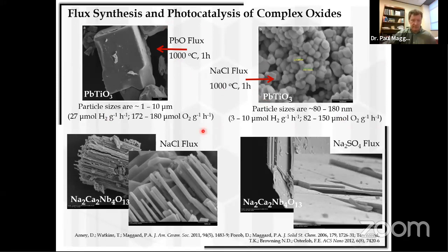are more active, because in these cases, you calculate the space charge width at the surfaces here. And they're actually quite large, on the order of several micrometers for lead titanate. And so the larger particles support that deeper space charge width, whereas it vanishes for the much smaller particles here.